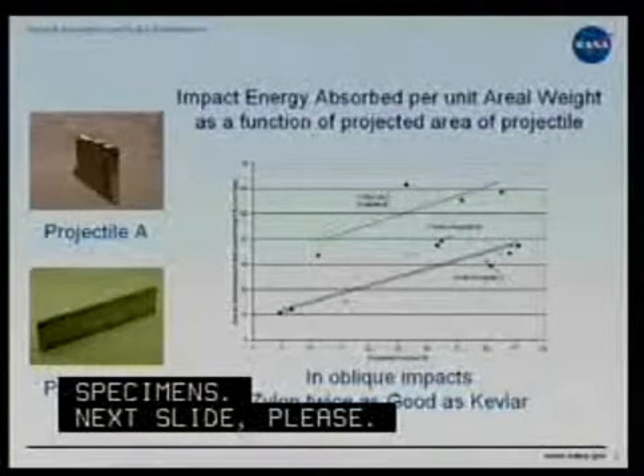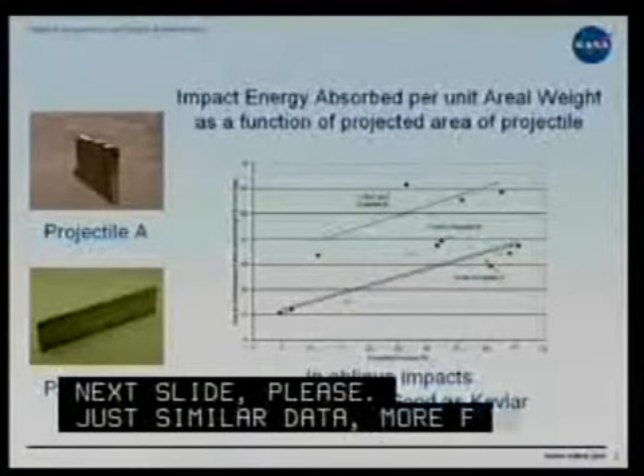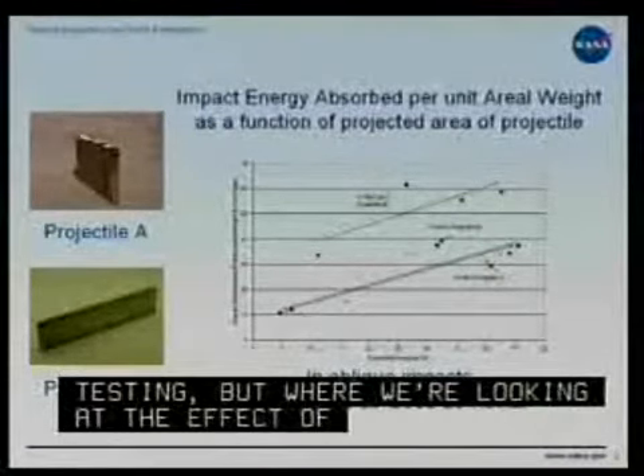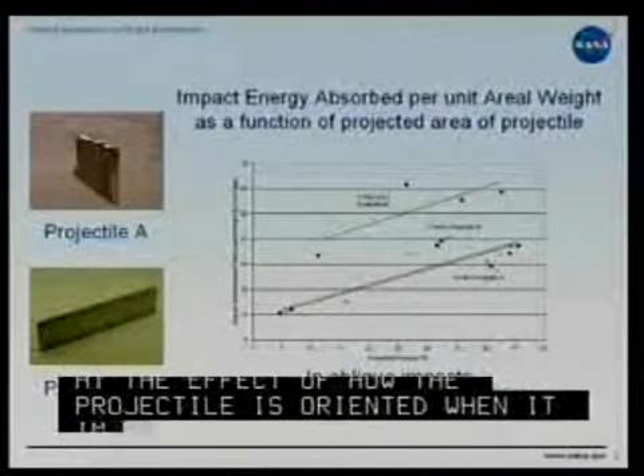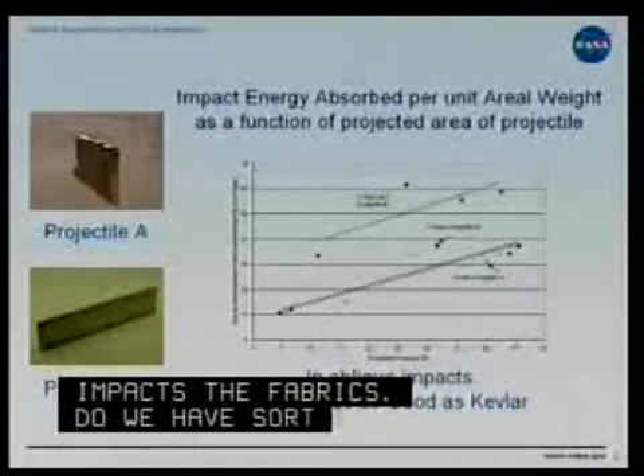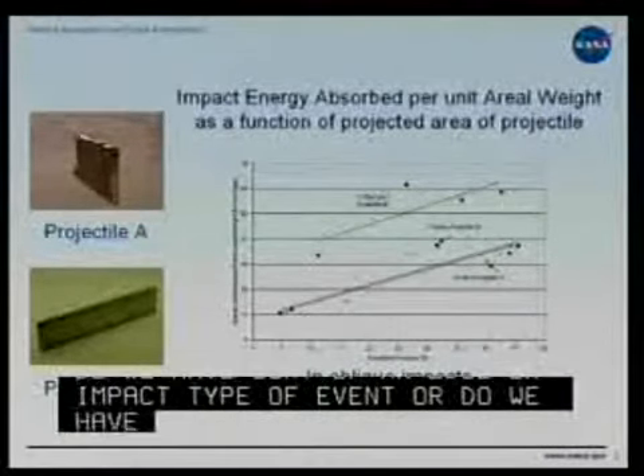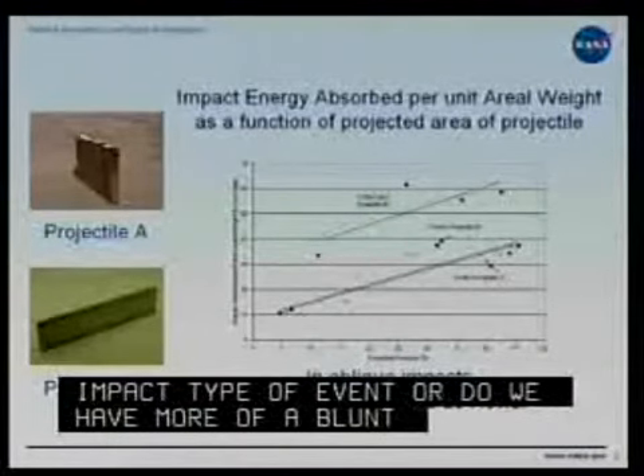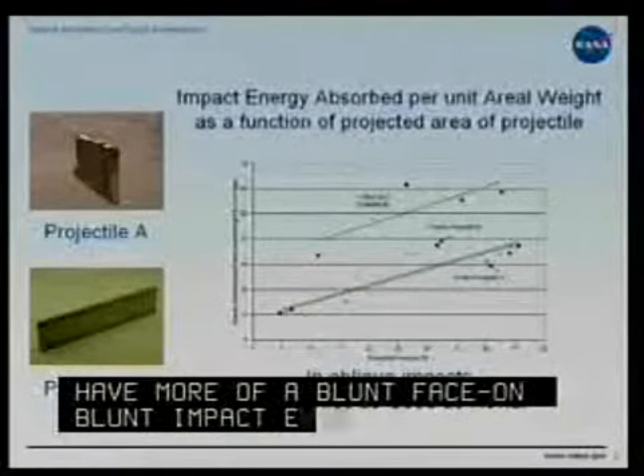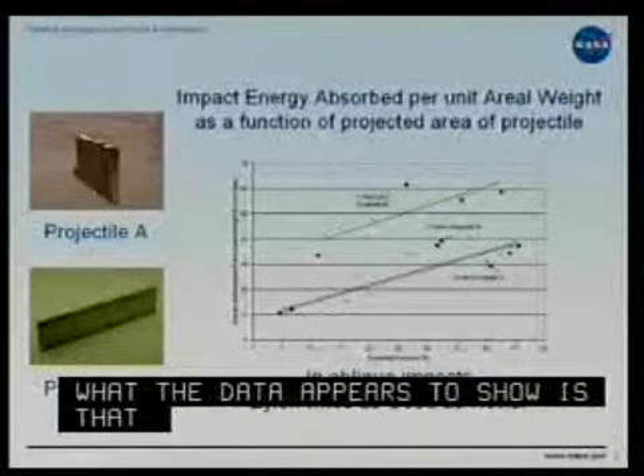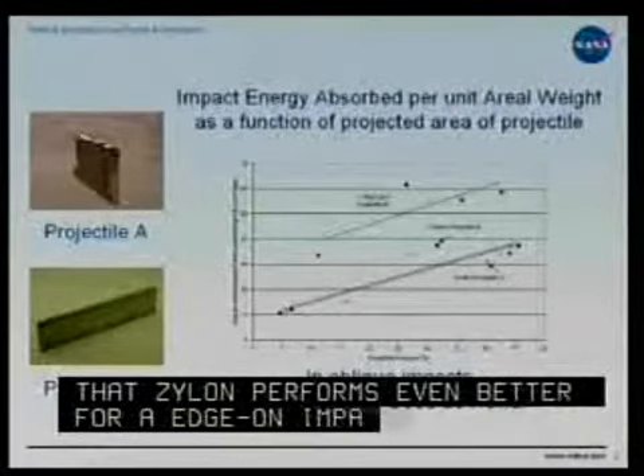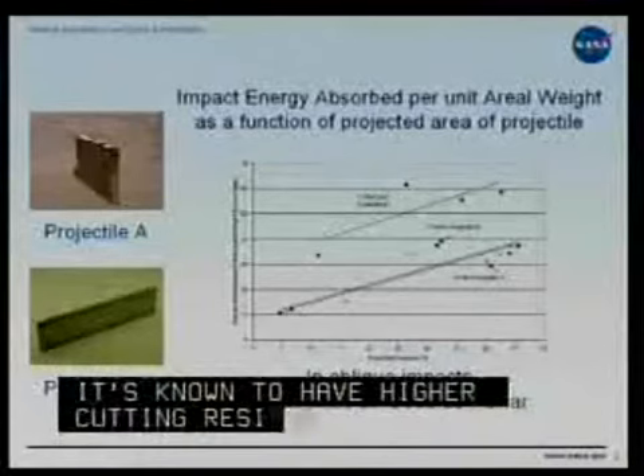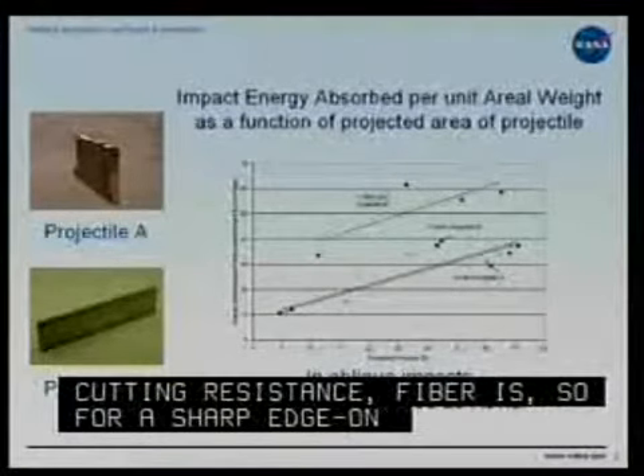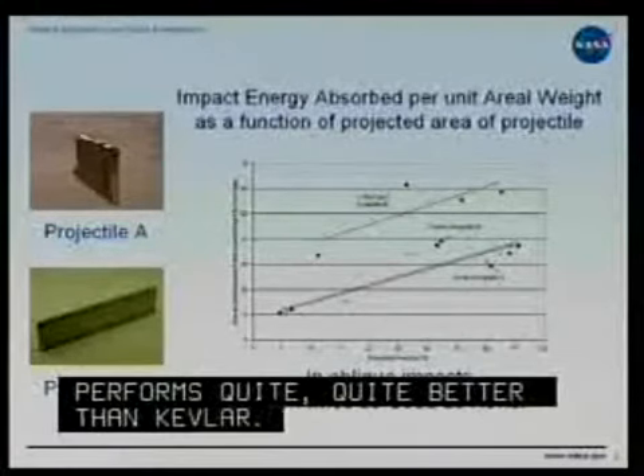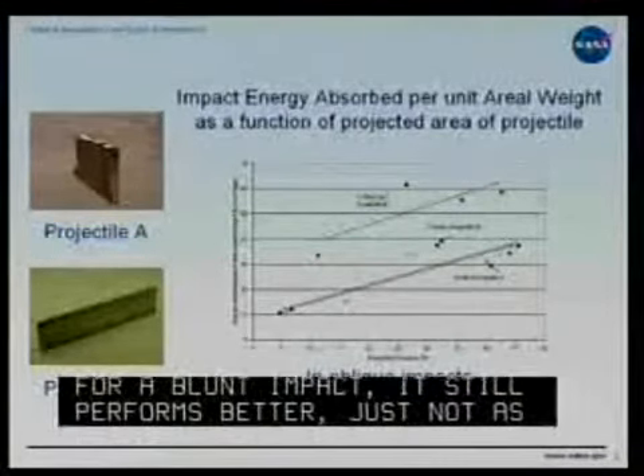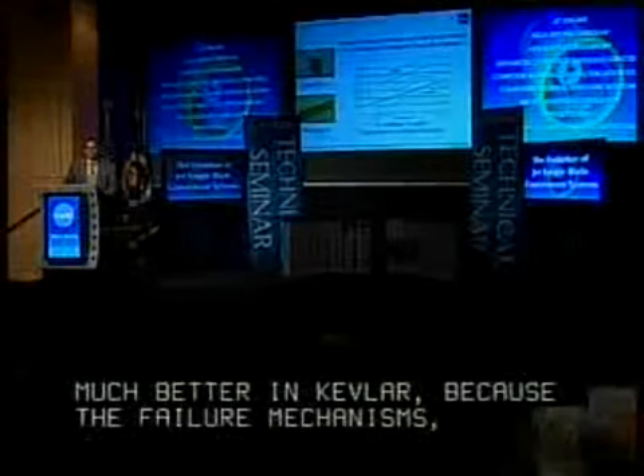Just similar data, more fabric testing, but where we're looking at the effect of how the projectile is oriented when it impacts the fabrics. Do we have an edge-on impact type of event, or do we have more of a blunt face-on type impact event? And what the data seems to show is that Zylon performs even better for an edge-on impact because it's known to have higher cutting resistance. For a sharp edge-on impact, it performs quite better than Kevlar. For a blunt impact, it still performs better, just not as much better than Kevlar, because the failure mechanisms of the fabrics are different depending on those 2 scenarios. So, next slide.